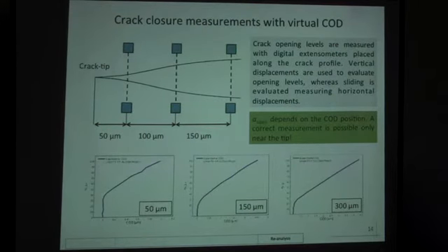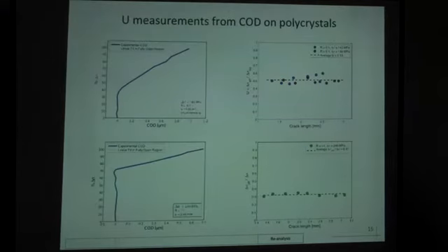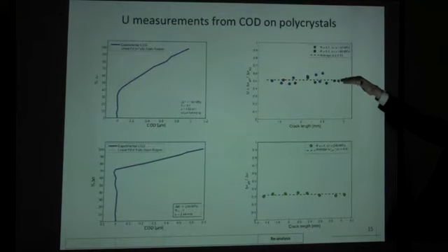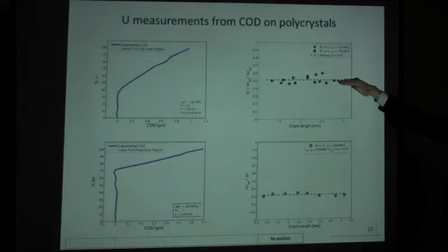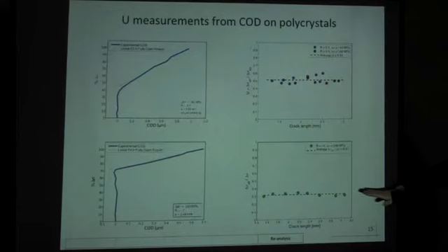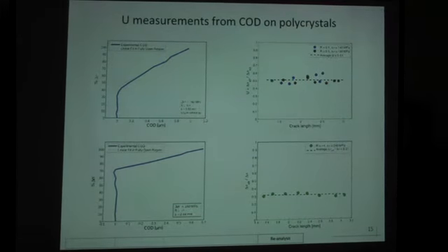So we carried out the experiment both at a stress ratio of 0.1 and a stress ratio of -1. Approximately our range for stress intensity factor range was between 15 and 20, and this was approximately the result for stress ratio 0.1. The U, that is the ratio of the delta sigma effective versus total, is approximately 0.5, and at stress ratio -1 it is approximately 0.3.